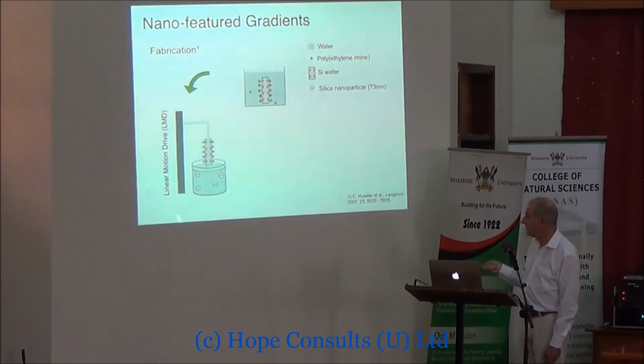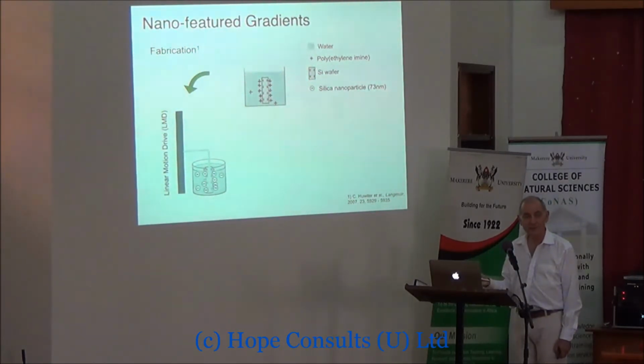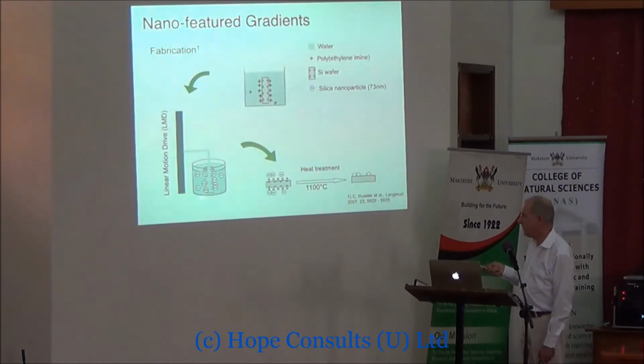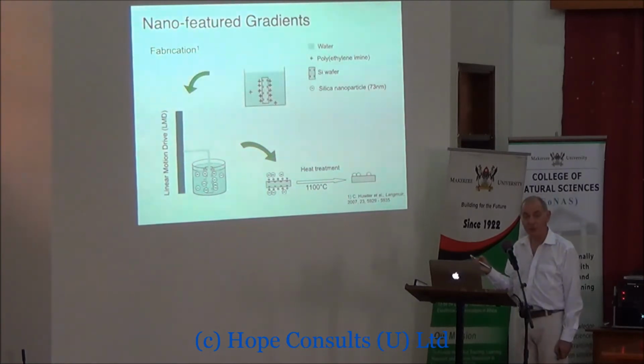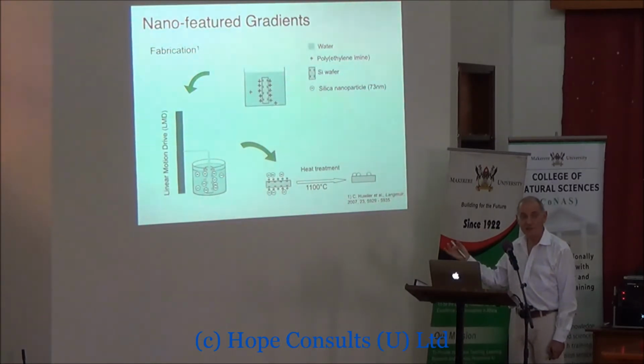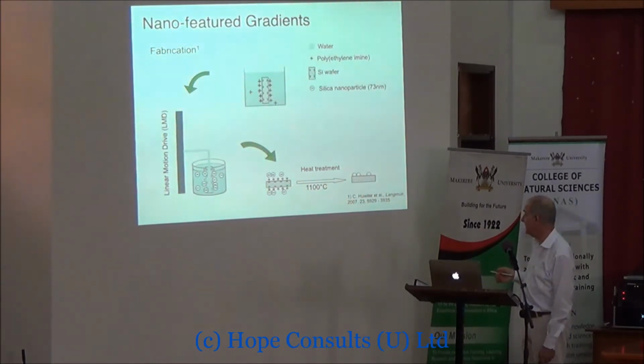And we used our favorite tool here, our linear motion drive, and we dipped it in slowly, and they stuck to the surface, but the longer it's in there, the more nanoparticles stick, and so if we dip it in slowly, then we have more nanoparticles at one end than the other, so we have a roughness gradient on the nanometer scale. And we don't want that polymer there, it was only there to help us make the gradient, so we burn it out. We put it in a furnace, we burn away the polymer, and we turn up the temperature even higher, so we actually get sintering of the nanoparticles into the silicon oxide on the surface of the wafer, and then the thing is fixed. Those particles aren't going to come off anymore. It's just a pure silica surface with a roughness gradient on a nanometer scale.